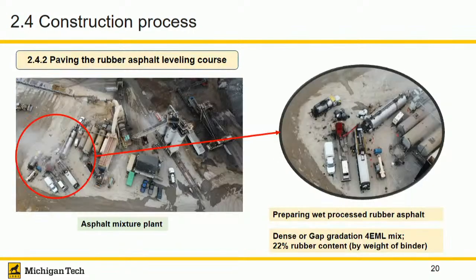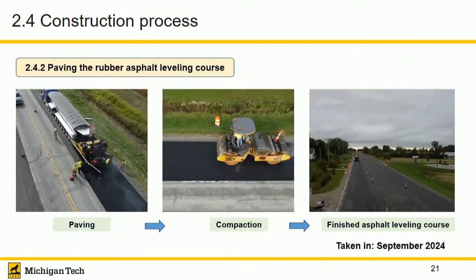And then, of course, we place it on. This is how they prepared the materials here, how they really prepare it from the PG 52-28, and how to really modify it with rubber materials. So then, of course, with the high content of rubber materials here, roughly 22% by weight of the binder. So it's pretty high content here. And of course, the temperature used here was pretty decent, very decent. All right, here is when the rubber asphalt is prepared.